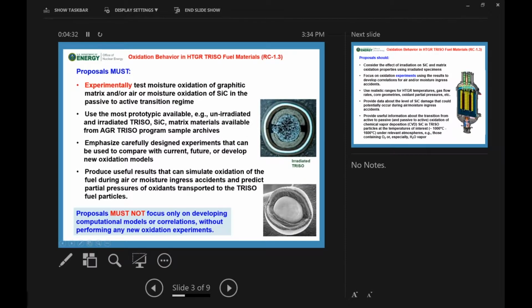So our proposals are geared towards having experimentally driven applications. We want to test the moisture oxidation of graphitic matrix and then air and moisture in the silicon carbide layer in what is known in the chemical transition regime from passive to active. We use the most prototypical available materials. We have unirradiated and irradiated TRISO that you can request, or you can use surrogates. We will work with you on that. And we emphasize that we want carefully designed separate effects experiments that can be used to compare with current, future, or developmental models for oxidation.